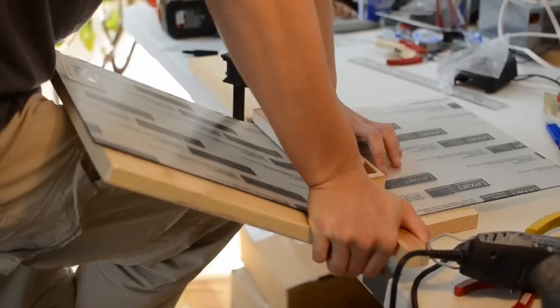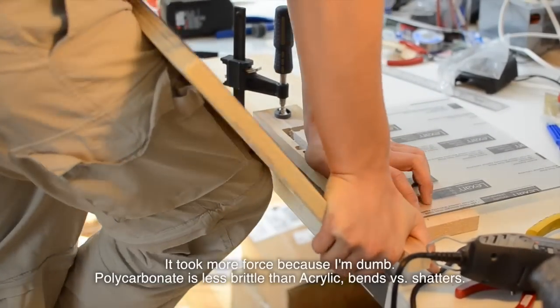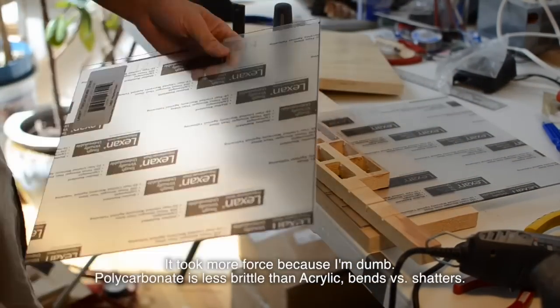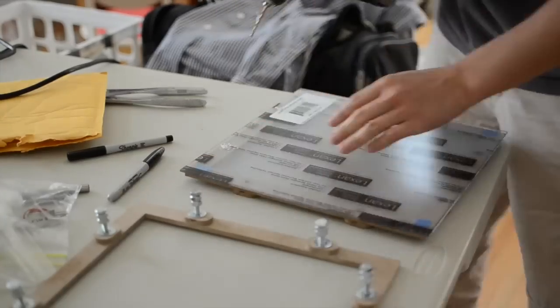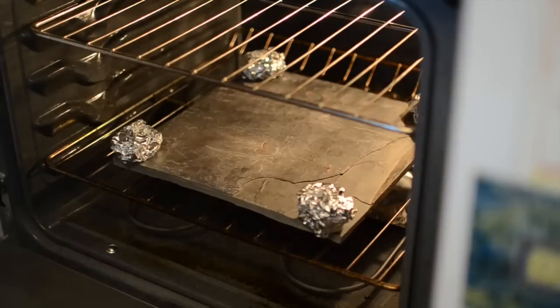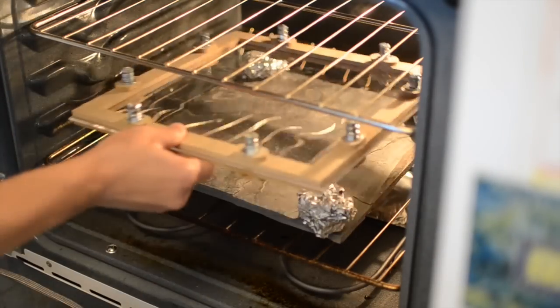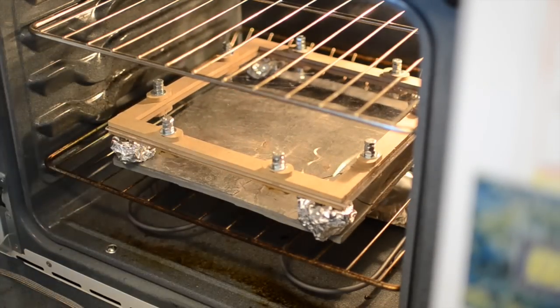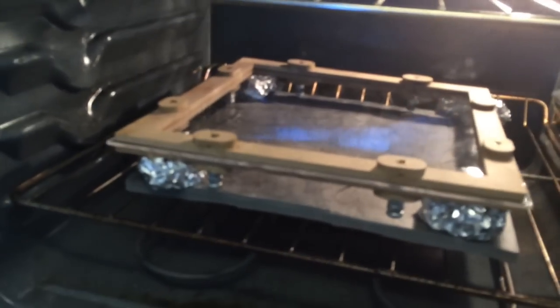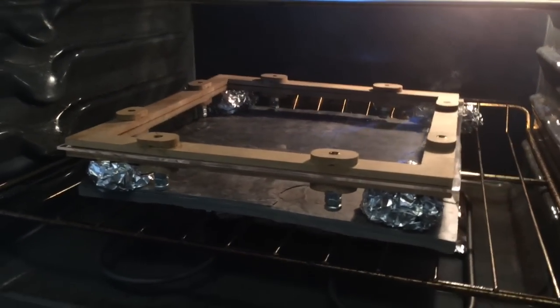It took more force than I expected, but I got a clean fracture across the width of my acrylic. I drilled a matching hole pattern for the support frame, bolted the plexiglass in, and set it in a 350 degree oven for a couple minutes. From my casual internet research, I was looking for the plastic to start drooping under its own weight.